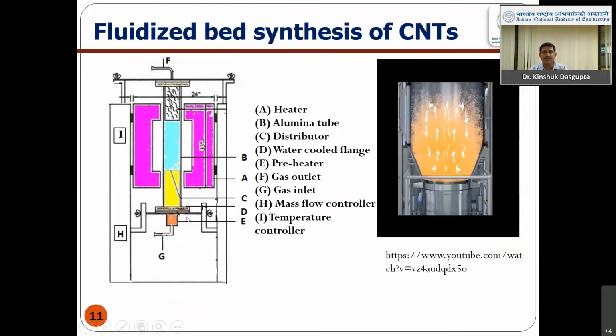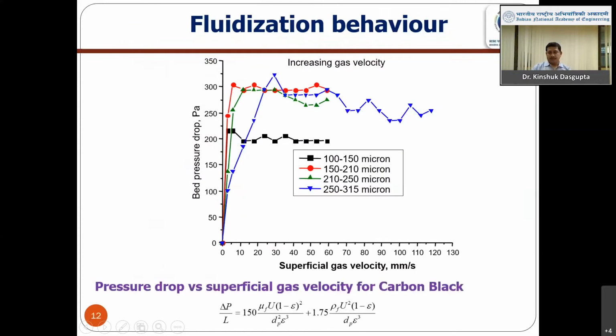If I see this schematic, argon along with hydrogen, we pass through this, and here the carbon black is fluidized, and once the temperature is reached, here we keep the ferrocene, which is a preheater region. So from here the ferrocene vaporizes and comes here, and on cracking it deposits iron nanoparticles here, and then carbon and hydrocarbon come, they also get cracked and carbon nanotube grows. How they grow I am showing in the subsequent slides.